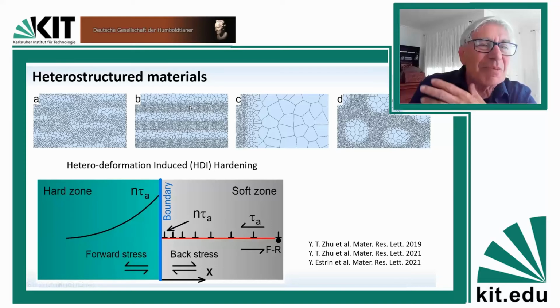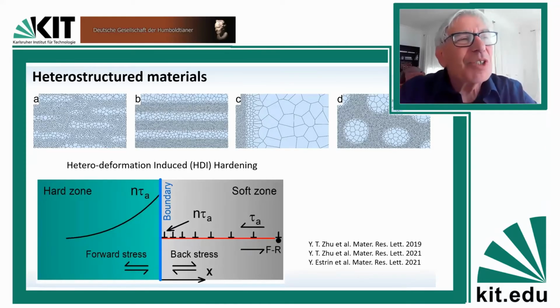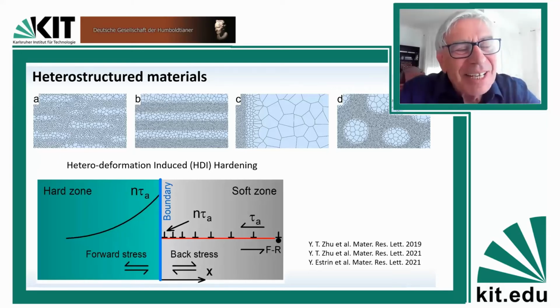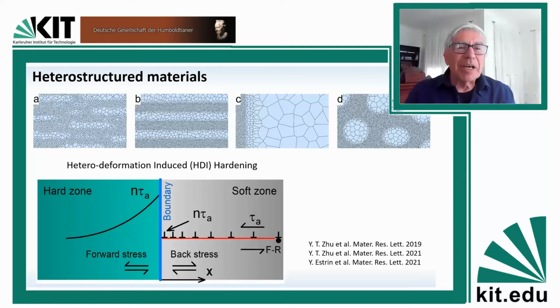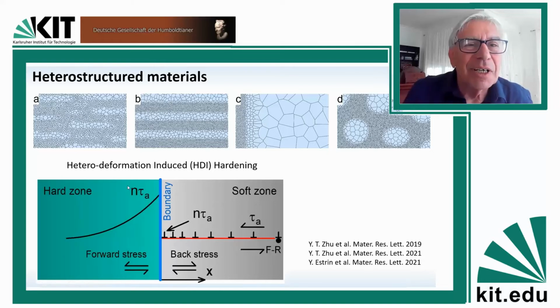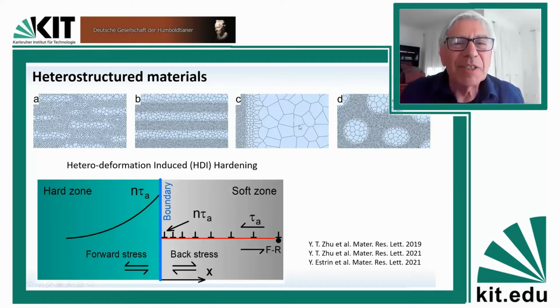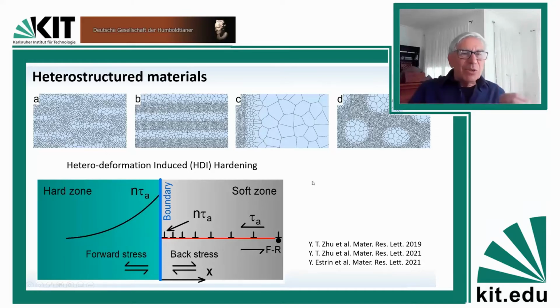Again, most processes give you a material which is non-homogeneous. So heterogeneity is intrinsic in the materials. But if it becomes a controllable inhomogeneity, if you can engineer that in a particular way that gives you the best properties, like producing layered materials with a coarse grain layer alternating with the fine-grained ones, thus changing periodically the strength of the material, or gradient materials from surface into the bulk. If you can do that in a controlled way, then you have a tool to design materials with programmable properties.